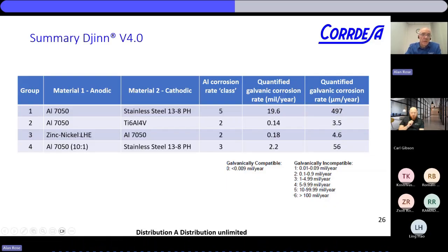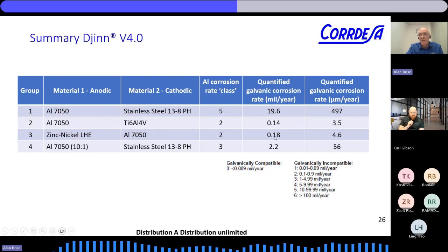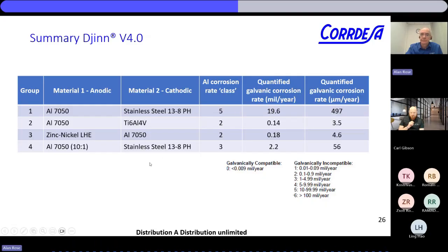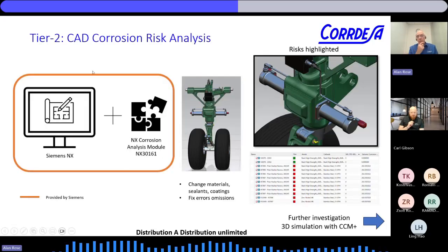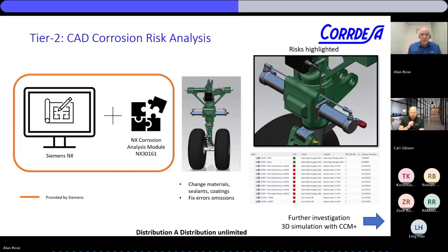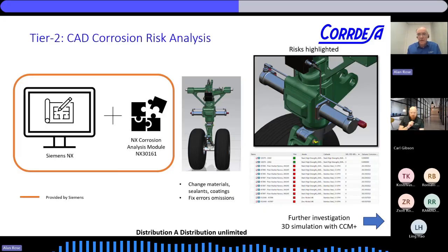Now, maybe it's cheaper to just coat your fasteners, like a zinc nickel coating, a sacrificial coating. So here it's swapped around. So now the aluminum has become cathodic, so it's not corroding. That's a good thing. And the corrosion rate is really kind of a consumption rate of your zinc nickel. So you can see how you can do that pair by pair, and it's still quite fast.